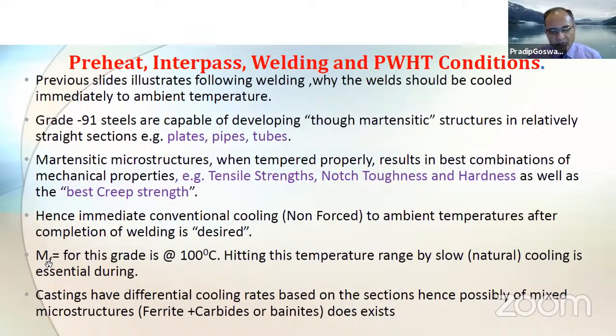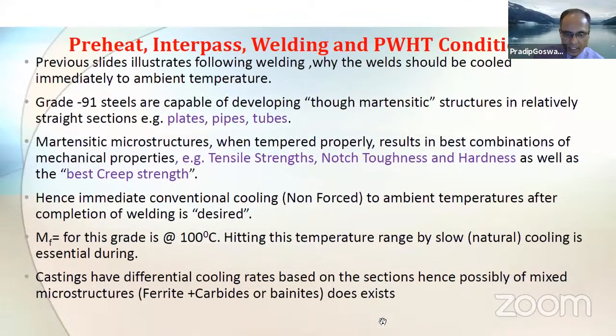MF, the martensite finish temperature for this grade, is approximately 100 degrees centigrade. Hitting this temperature range by slow, that is natural, cooling is essential after welding. Castings have different cooling rates based on the sections, and hence there is a possibility of mixed microstructure. Ferrite, carbides or bainites may exist.